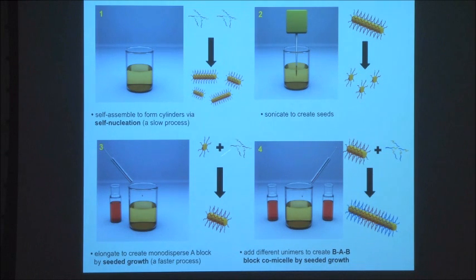And then to the seeds, you add the unimer. This is the seeded growth process. This is a faster process than the self-nucleation. So all of the unimer that you add adds to the seeds. It doesn't form new cylinders. If it did, it would be a pretty useless process. So this is a key that the addition of the unimers to the seed is much faster than the formation of new micelles from the unimers. So this allows these structures to grow, and then you can add another unimers of another block copolymer on the end to make block structures.